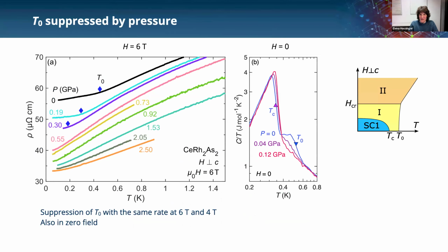And here's a summary of those results. So first, I show you data of resistivity versus temperature at 6 Tesla, where the superconducting state is suppressed, so we are here. And the T0 is nearly unchanged. And so we observe T0 as this kink in the curve. And you can see that by increasing pressure, it's strongly suppressed.